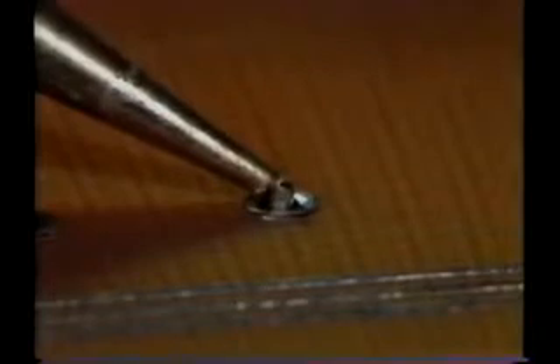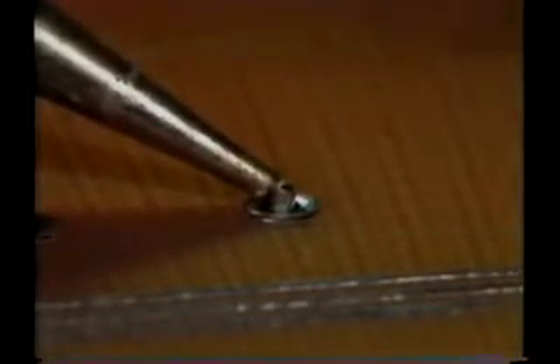Here we have a burnt board, and this is a lifted land. These conditions can occur when too much heat is transferred to the board. Pushing down hard with the iron can also help lift a land. Failure to allow cooling of an area between heat applications can also result in a lifted land. These are visible signs that the iron was left on the board for too long, or that an iron with too high a temperature was being used.